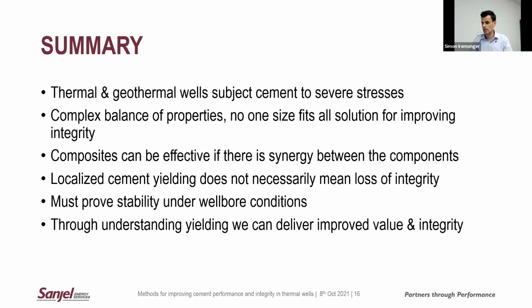Yes. And I didn't have the time to go into great detail on that. If you look back at that original SPE reference, we did ultra high temperature curing on those, with scanning electron microscope analysis all the way up to approaching 700 F, the limit of Portland cements. So I would say yes, traditional fibers melt, but if you understand the chemistry and potential decomposition pathways, again, yielding or failure doesn't mean that you don't have performance there. So it's a case of some complex chemistry going on, but by understanding that, we were able to validate that that product was still stable at those steam injection temperatures.